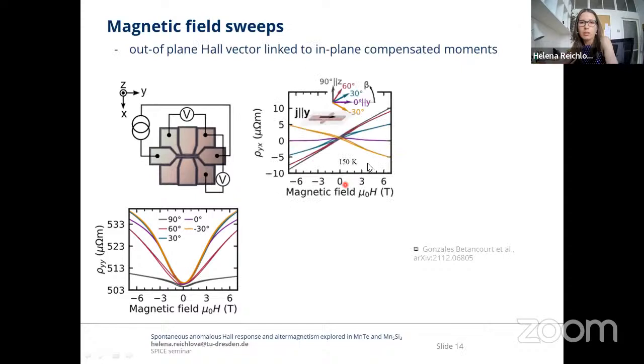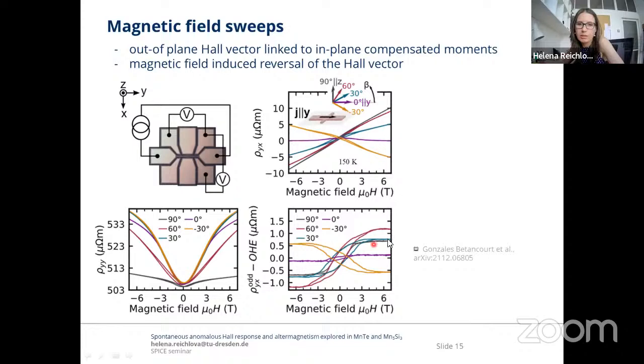However, when we look at the transversal signal, on first look it might look dominated by the ordinary Hall effect. And already here, one can see that there is some sort of splitting, that it's not only the ordinary Hall effect which is present. And when the linear background is subtracted, a clear, saturated, and spontaneous signal remains. So what is happening here?